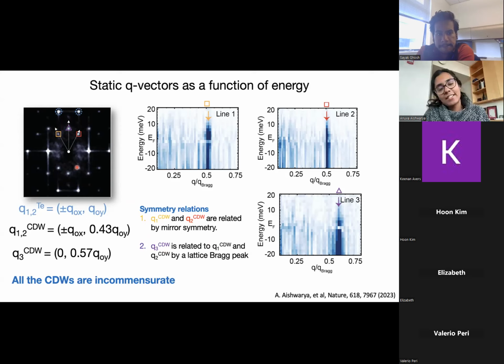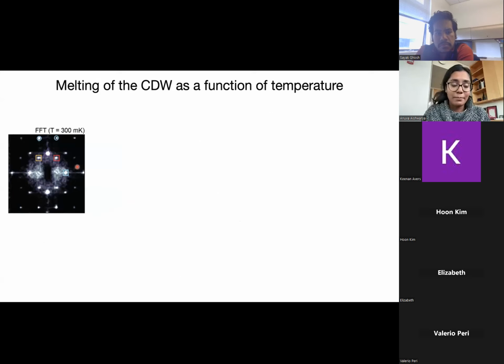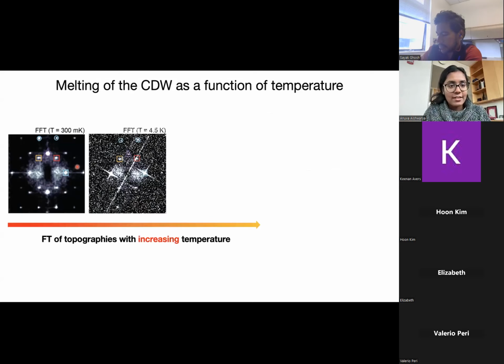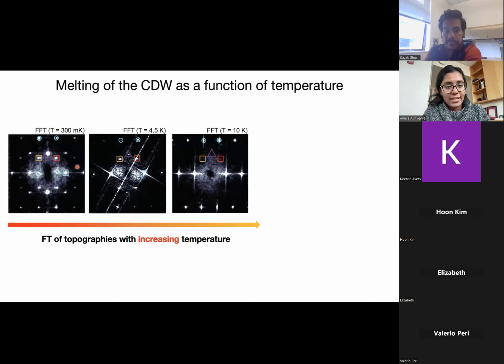So we can track these CDWs as a function of temperature. Now I'm going to show FFTs of topographies and density of states maps as we increase temperature. So this is 300 millikelvin. This is 4.5, it's weak. And by 10, we see that this is gone.